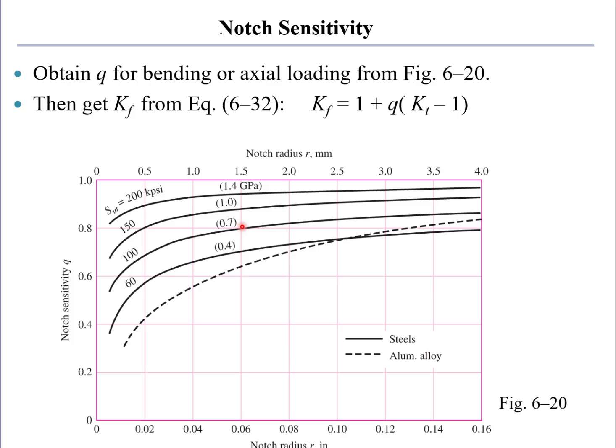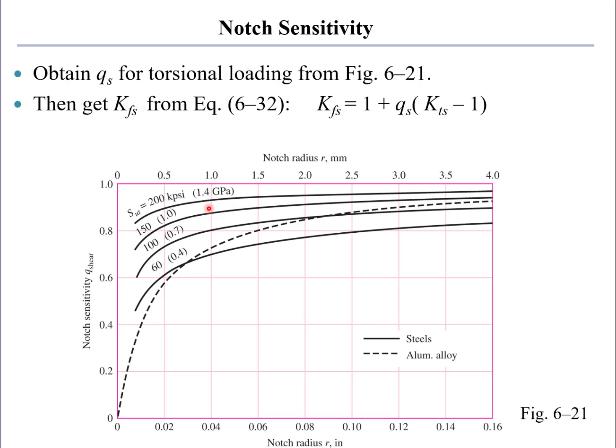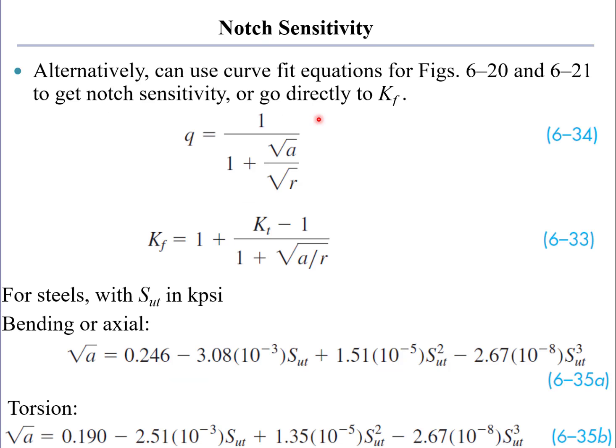The other thing that's important is that the notch sensitivity depends upon the loading, just like the stress concentration factor depends upon the loading. For axial and bending stresses, this is the notch sensitivity curve. If we move to shear stresses, we have a different notch sensitivity curve. This is the shear notch sensitivity. And you note that there's an elastic stress concentration factor in shear that is different from that in bending or axial loading. So we have to take all of that into account when we go about trying to calculate a fatigue stress concentration factor. That is a huge nuisance.